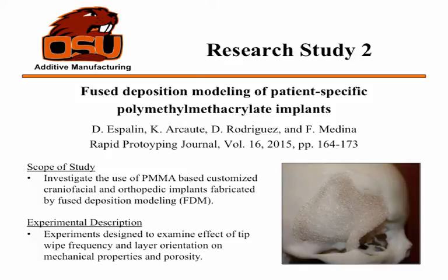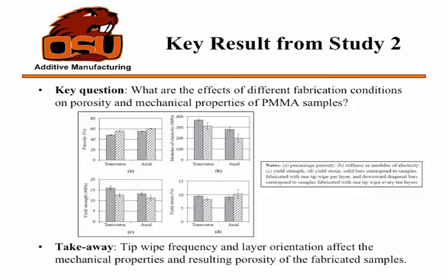And importantly, porosity, because porosity is a key factor in muscle growth and bone growth. It really helps the biocompatibility of these implants. So what effects do different fabrication conditions have on the mechanical properties? Porosity had a large impact, as you can see in the yield.